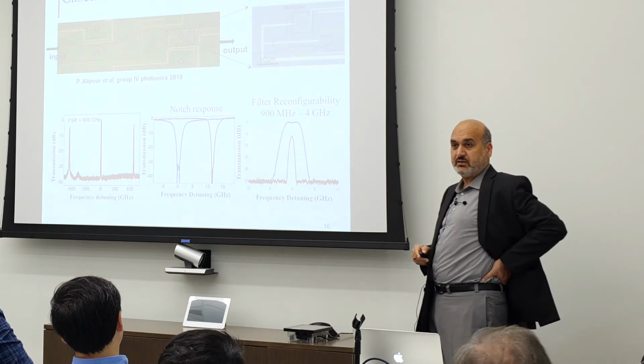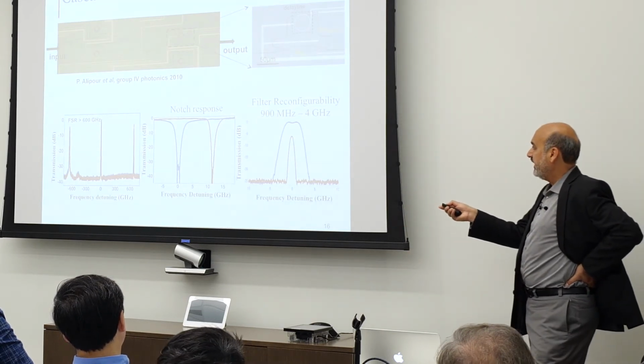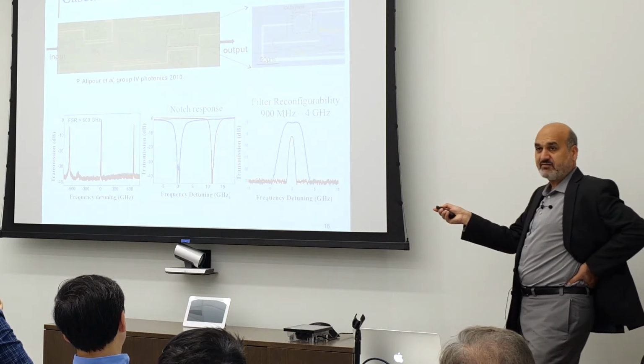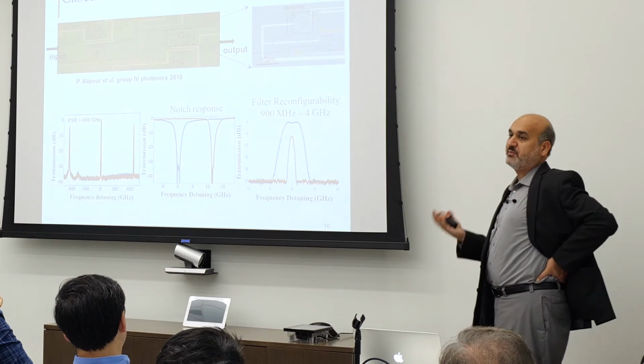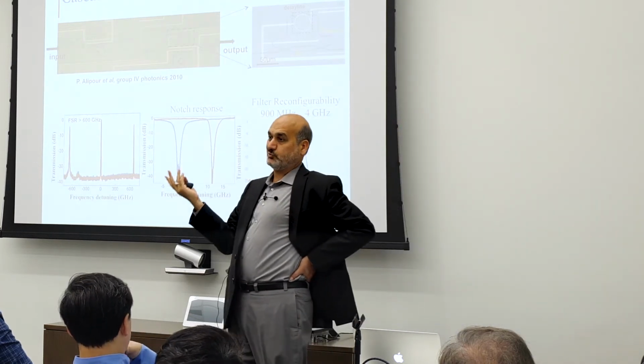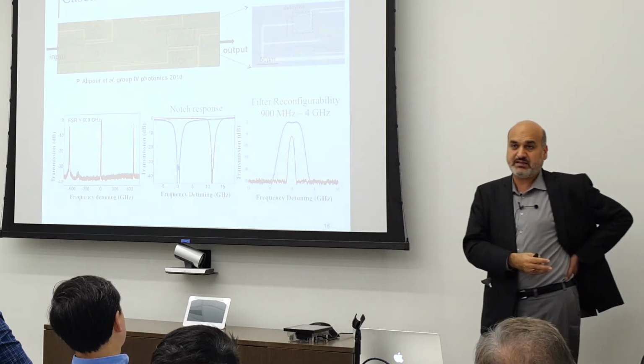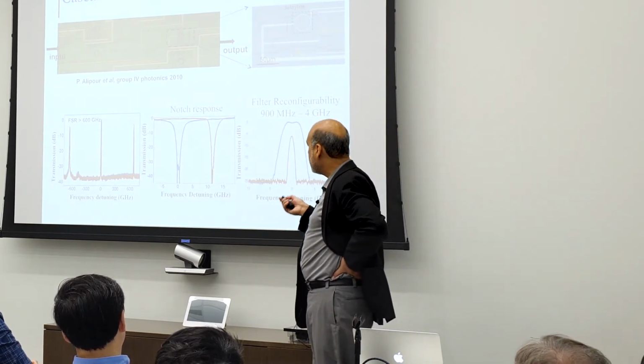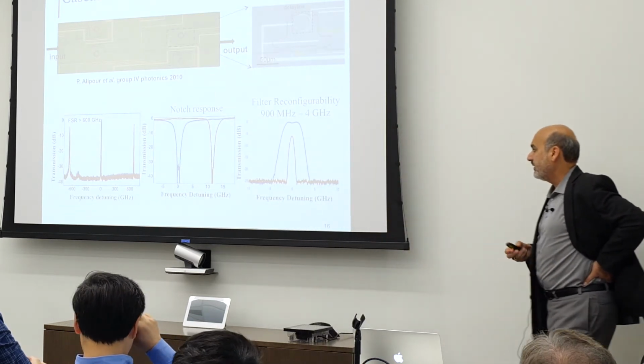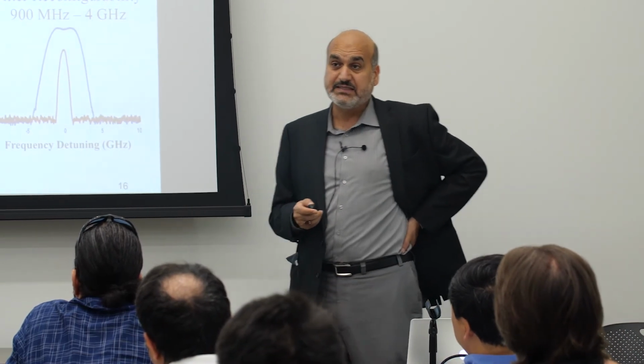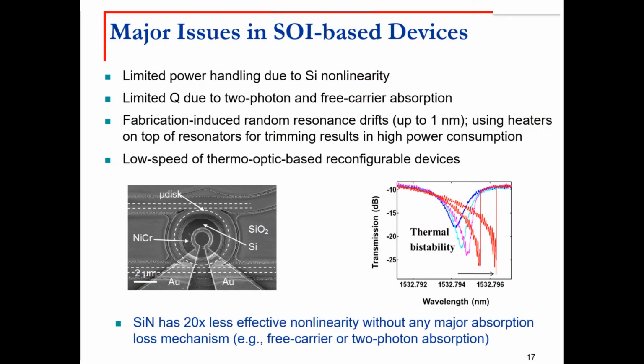The same filter structure under a different set of input control signals will act as a bandpass filter, in which you have control over the center wavelength and also the bandwidth. So it's a kind of multi-purpose filter chip where you only change the control signals, and based on those control signals, it gives you a different functionality. Potentially, with thermal heating, it can operate at about 100 nanosecond reconfiguration time. So it's really fast for a lot of applications where you want to sweep the spectrum and monitor the spectral content. Well, if silicon is so good, then why should we go for hybrid materials?